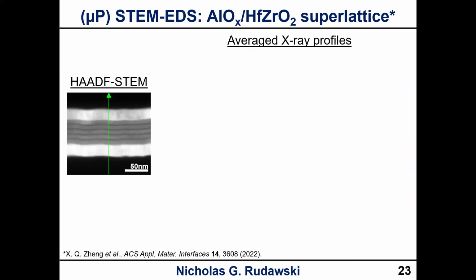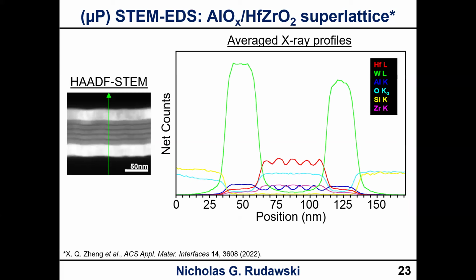So if we also look at a profile here, we integrate the profile across the interface, and this is not ideal because the interface does have some undulations to it, but we can still do it anyway. It'd be better if they were perfectly flat, but they're not. But anyways, we can see this in the averaged X-ray profiles as well, that we're resolving the alumina.